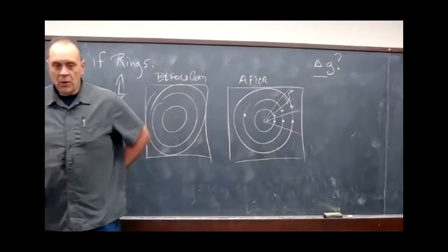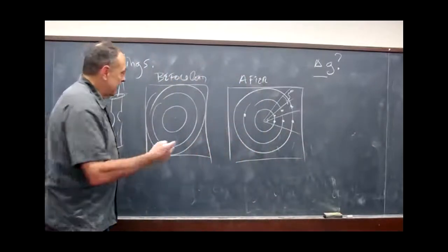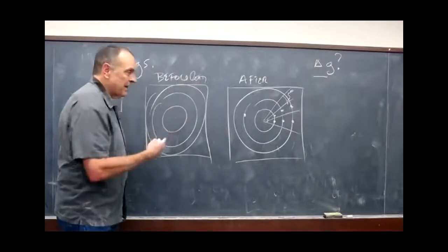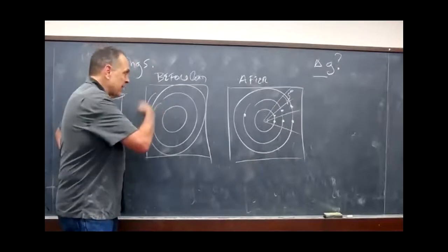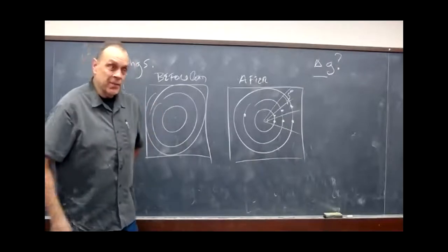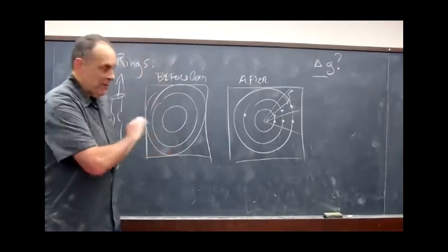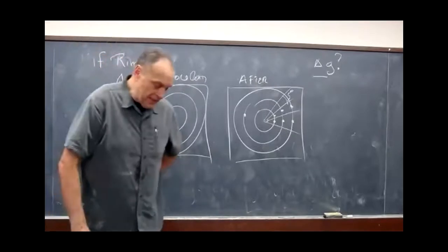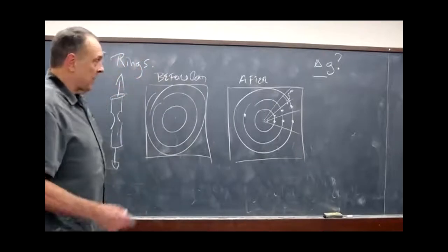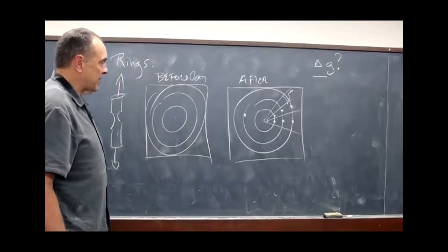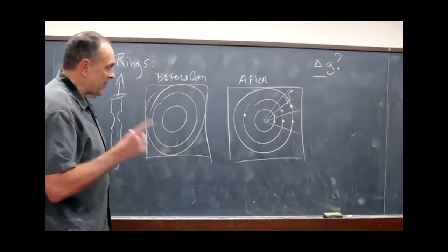So really what's happened is that I have so many crystals in the diffraction volume, there are still spots under here. But now there's so many spots that they just overlap. And so I can't do my cool little magic thing that I do with the spots and identify which strains go with which crystals, or which spots go with which crystals, because I don't know.